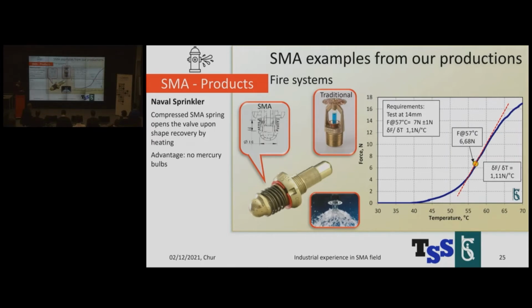So, yeah, you need to consider also the thermal hysteresis that you have on the springs. Well, in this case, it's not so important because you have a thermal hysteresis when you cool it down. But in case of fire system, you just have a heating, so you do not have a hysteresis. There are several factors that you need to consider in the design and in the production process. Mm-hmm. And I guess you also have to take into account the batch of material that you receive, and can you test that?